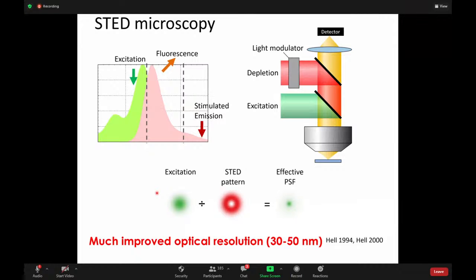But if I am able to do it like this, I have an excitation source which looks like this. Let's say this is a 200 nanometer beam, but I'm going to generate a STED beam pattern. Any molecule within this beam is not going to have any fluorescence emission, because they are depleted by using this stimulated emission, right? So no emission from this sort of beam pattern. Now if you overlap these two, effectively you are not getting emission from the STED pattern beam, you are only able to get emission from the overlap of these two beams.